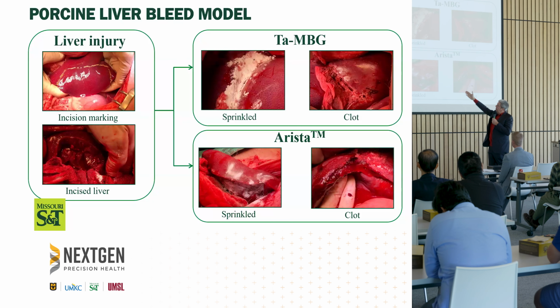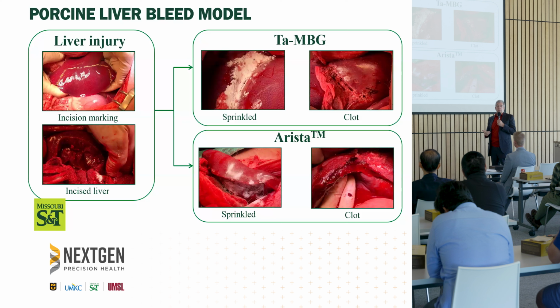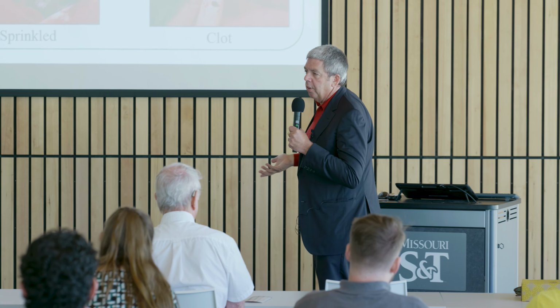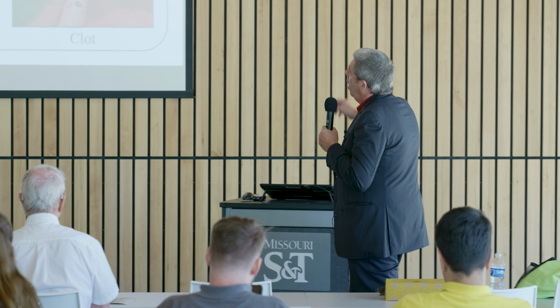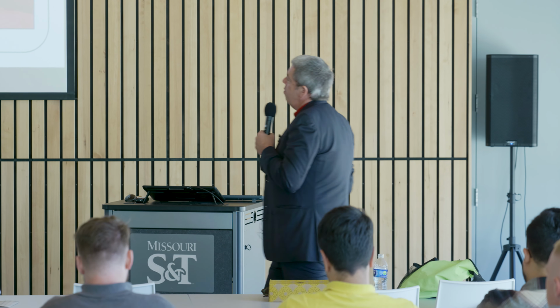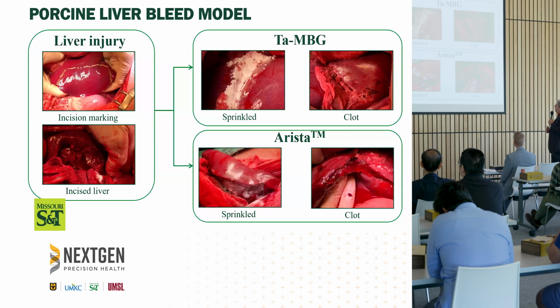We take a pig and we try and simulate a gunshot wound. And we cut away, you can see from the bottom image, it's quite good, it's very light in here, so you can't see too much detail. But you'll see that about a third of the liver has been removed. The liver is highly vascularized, it bleeds like crazy. You've all heard of the phrase bleeding like a stuck pig. That's where it comes from. And what we did there is try to see if our material or Arista could stop that bleeding faster.